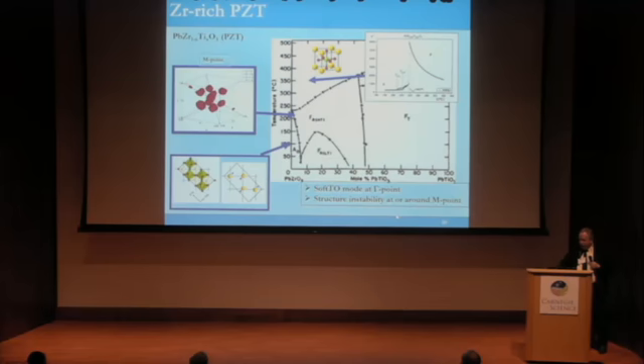And then let's return to lead zirconate titanate. So we are interested in this small region where there is a very low concentration of lead titanate. And look here, the especially complicated picture we do see next to the M point. So we have many satellites of the first order, of the second order. The question is, what is the origin of these satellites? There were several attempts to describe them as a result of some antiphase domains, but it doesn't work in detail.